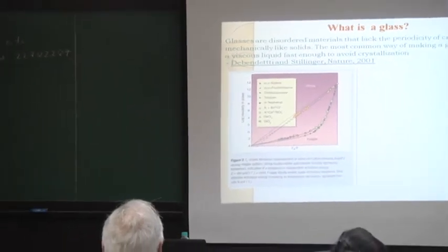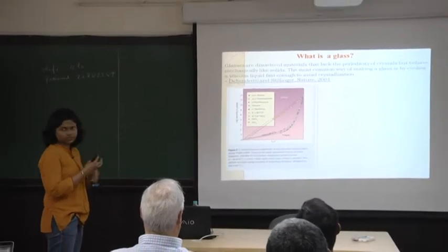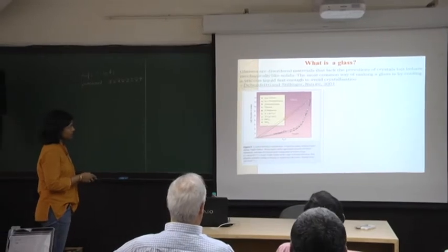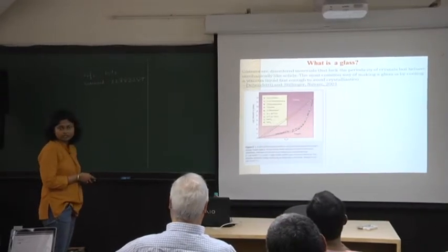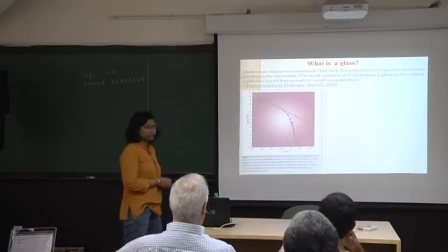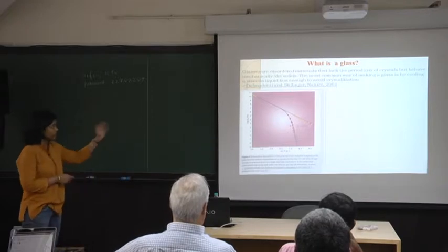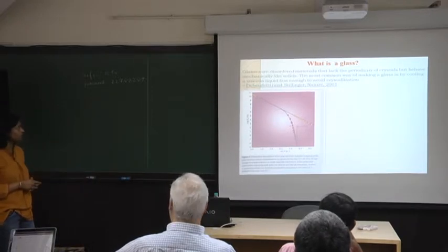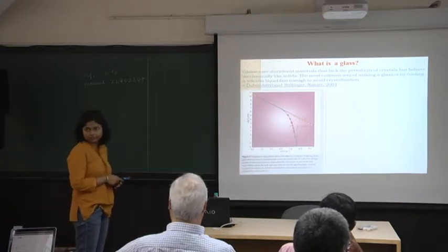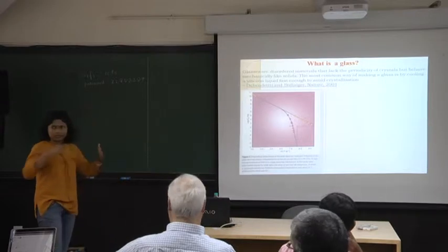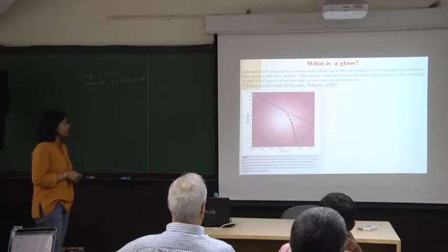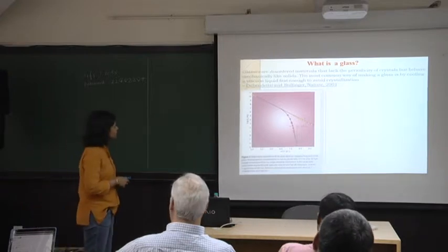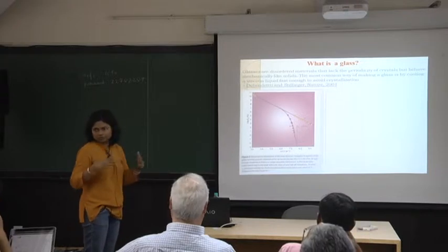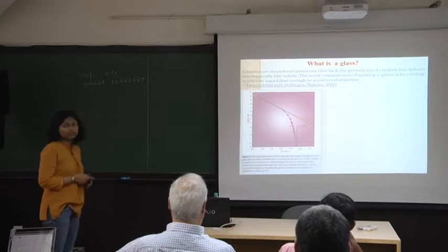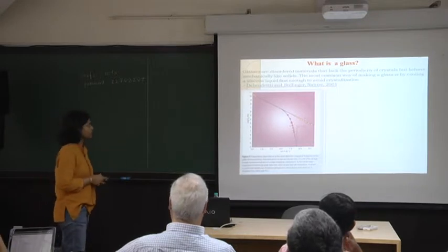In the case of fragile glasses, such as the ones that we are going to show you today, like colloidal glasses, there are also all these mixtures of organic liquids. As you can see, for these liquids, the approach to the glass transition is much, much faster. People also measure the dynamics. So this is a fragile glass forming material. It's a mixture of two organic liquids. This is a dielectric spectroscopy experiment. You just measure the frequency dependent dielectric data. You fit it to very well accepted functional forms, and you get the relaxation times, or in this case the relaxation frequencies out. And this is what you see.